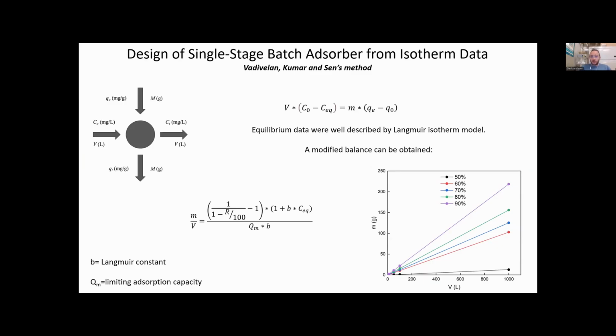From a chemical engineering point of view, it could be interesting just to start thinking about the design of a single-stage batch adsorber. By coupling the equilibrium law with the Langmuir isotherm model, it is possible to obtain a relation between the mass of the sorbent required to treat a specific volume of methyl orange solution by setting different removal percentages. So for example, in order to treat 1000 liters of methyl orange solution with a removal of 80%, just 150 grams of copper modified hemp fibers are required.